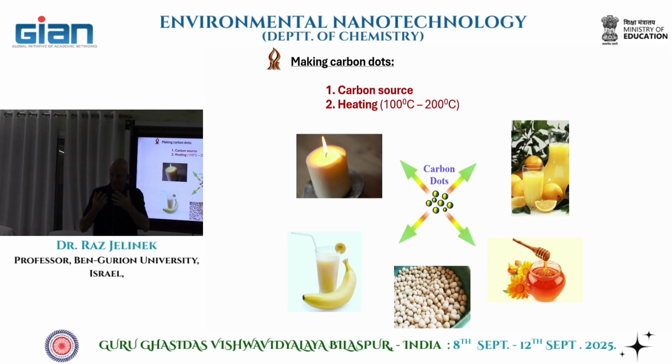And then it's more difficult to break the bonds because they are very stable. So that's what you do. You just break and break until you get small nanoparticles. If you give higher temperature, 500 degrees, 600, then you can take everything, break it completely, and get char. But this is not what you get here because you are very gentle.